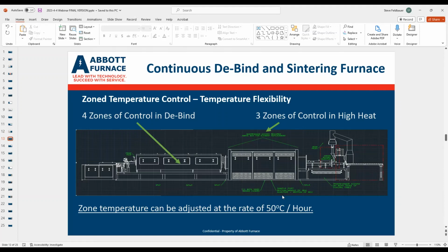design, four zones of debind in the front, three zones of high heat control. But what's nice here is you get a lot more flexibility with this type of furnace. I get asked a lot, well, how quick can I change over? Well, the truth is you can change over much more easily with this type of system than a batch. For a batch furnace, if I load 316 into my batch furnace, I have to heat it up, run my cycle, cool it back down, unload it, then I can change over to the next product. Now, depending on the cycle time and how you run it, that could be anywhere between 9 hours to 22 hours, right?